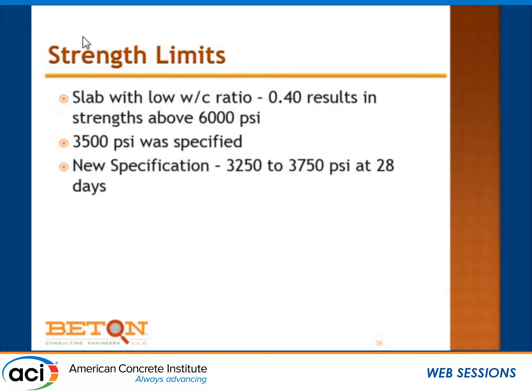And the salesman brought this to me, and I said, well, that's nice, but this is a physical impossibility. With normal ready-mix properties, even if you cheated and said, just make the water-cement ratio whatever, if we tried to hit this strength with no controls in place, we wouldn't be able to do it. It would require a standard deviation of about 150 in production. It's not possible. The salesman looked at me and said, well, that's bad because we already got five of these stores. So we went on and dealt with it.